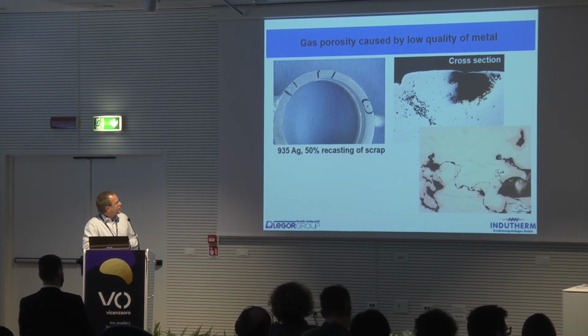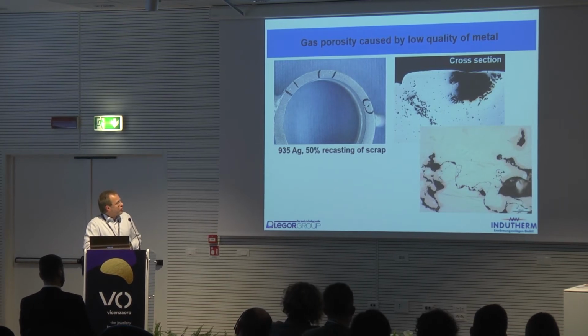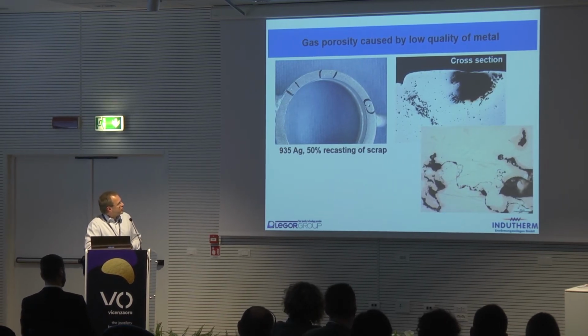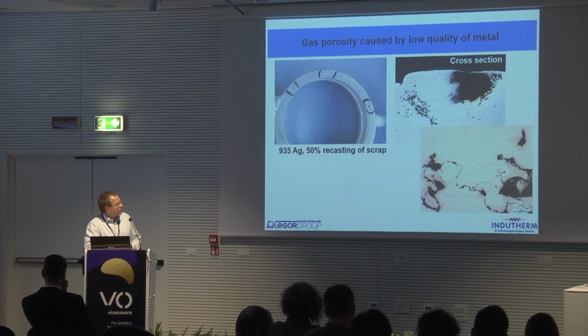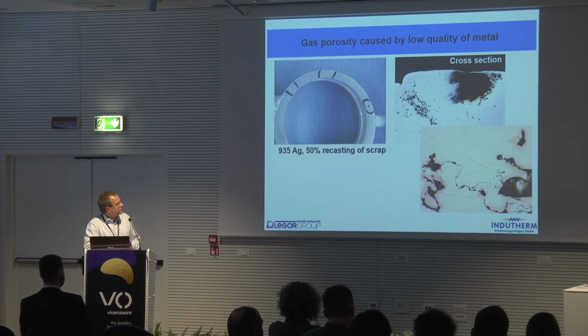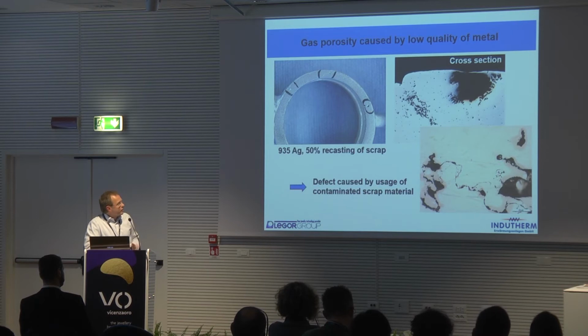Again, a case study here with some big gas pores on a ring shank of sterling silver. If you look with analytical equipment, with a microscope on microsections, we can look into the nature of the defects, and in this case we can see a lot of impurities, oxides, near to these gas pores. So very probably in this case, the defect was caused by the usage of contaminated scrap material.